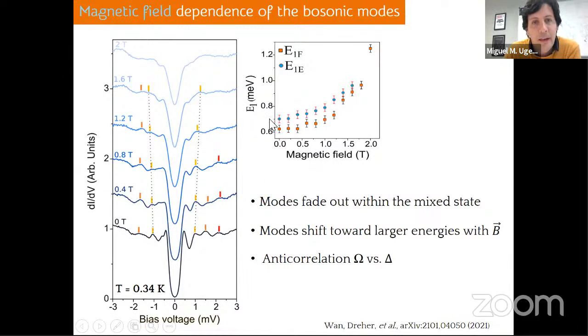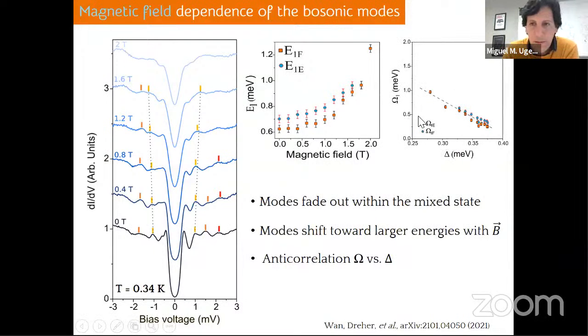So if we now plot the energy with respect to the position of the coherence peak, if we plot the evolution of omega, the binding energy of this bosonic mode, against the superconducting gap for each curve, you'll see that these two quantities are surprisingly anticorrelated. There is a clear anticorrelation between the binding energy of the bosonic mode and the superconducting gap. This is something that I plot normalized by 2 delta, and most of the values lie below 1, and I'll explain in a minute why.